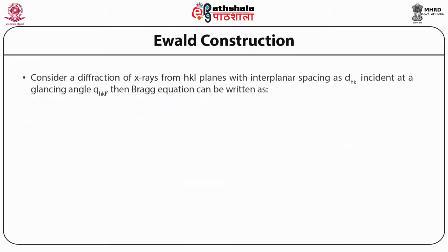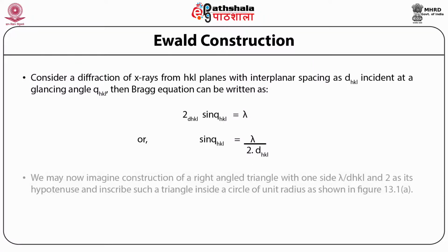Consider a diffraction of X-rays from HKL planes with interplanar spacing dHKL incident at a glancing angle theta HKL. Then the Bragg equation can be written as 2 dHKL sine theta HKL is equal to lambda, or sine theta HKL is equal to lambda by 2 dHKL. We may now imagine construction of a right-angled triangle with one side lambda by dHKL and 2 as its hypotenuse, and inscribe such a triangle inside a circle of unit radius as is shown in figure 13.1a.